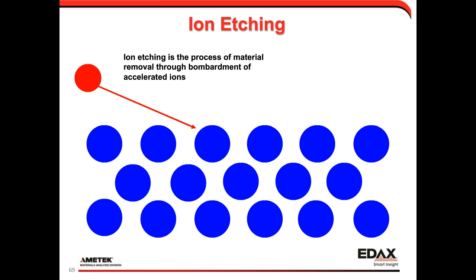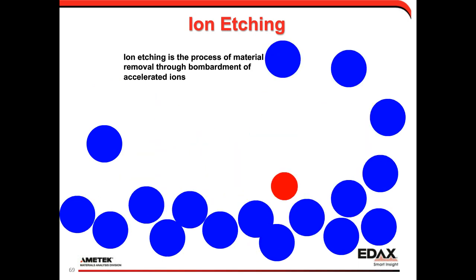Now, another growing application is the idea of using ion etching, and either broad beam or focused ion beam approaches, where basically we accelerate an ion of a material into the surface to remove material from our sample. So this is just a little schematic. Our ion comes in, it blows some material off, but of course, I tried to show schematically, it also forms a little bit of an amorphous layer. So as we do this, the angle of attack that ion comes in at will play a strong role in terms of the removal rate and also the deformation and amorphous layer that's residual, as well as the energy of the ion.